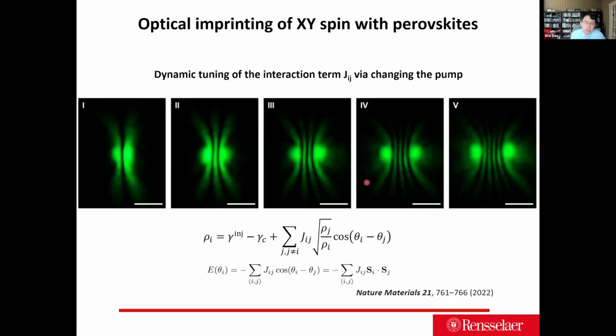So in comparison, with halide perovskite, we can, at room temperature, without bothering the cryostat, optically imprint the two BEC condensates. And by observing the center part, one can see the two condensates. These are out of phase, or these are in phase, and these again out of phase, and these are in phase. So optically, one can control the pumping condition to directly tune the interaction between the two condensates. And the polariton system automatically minimizes loss.